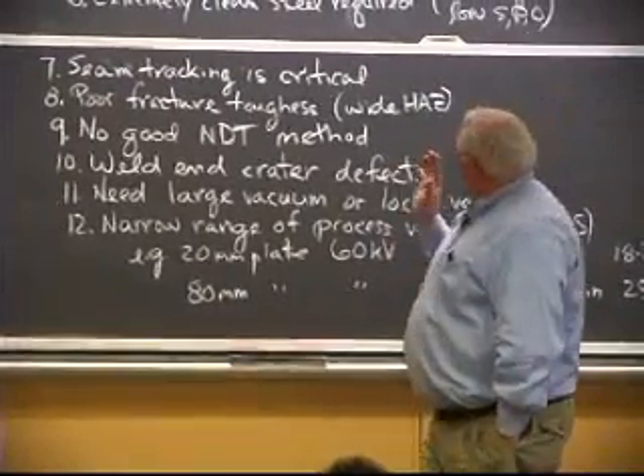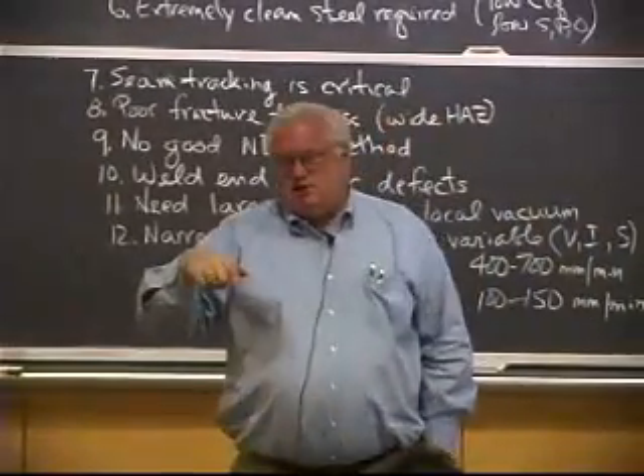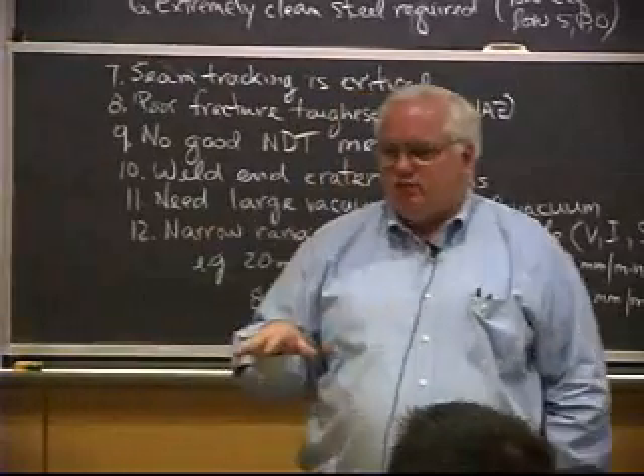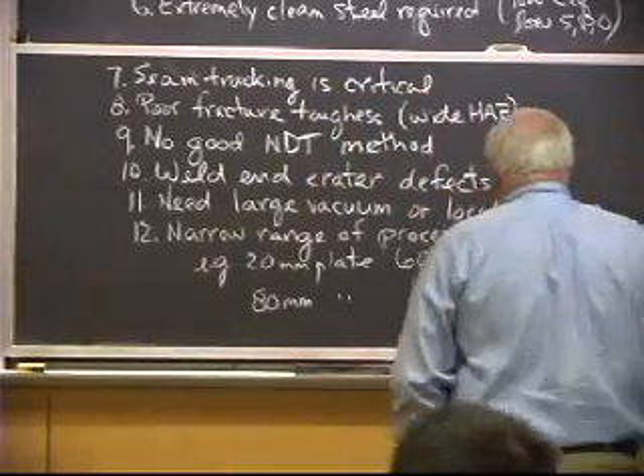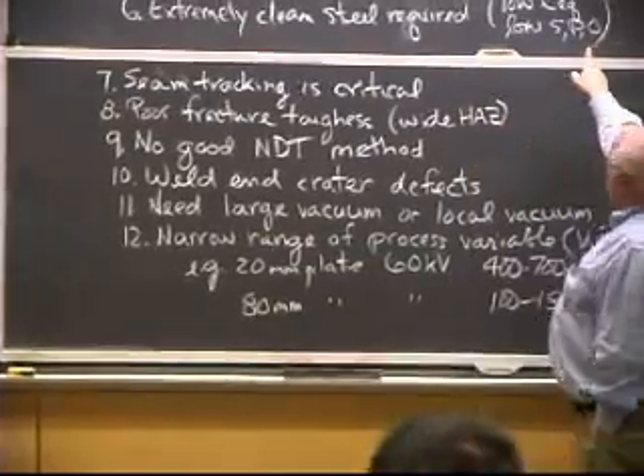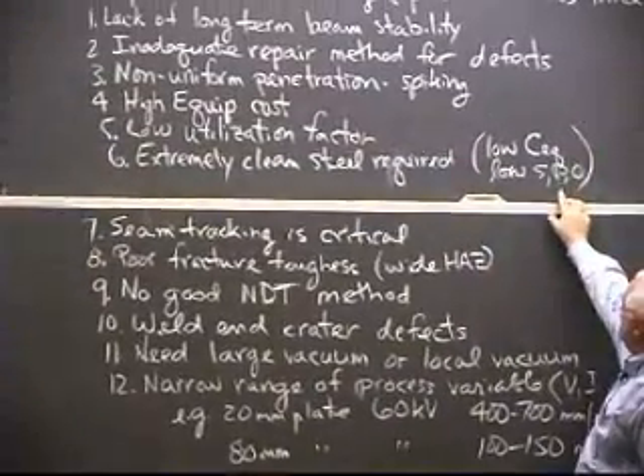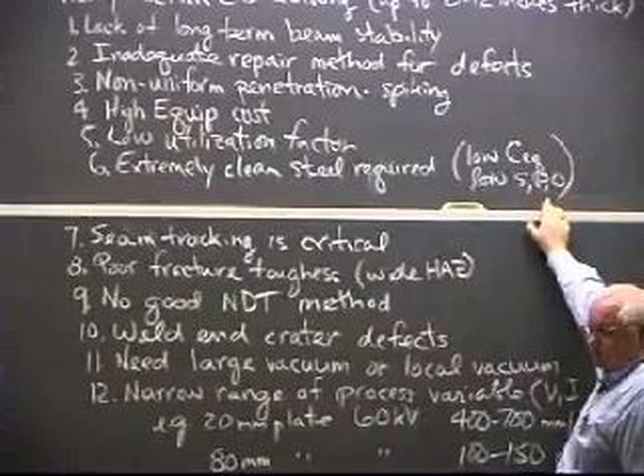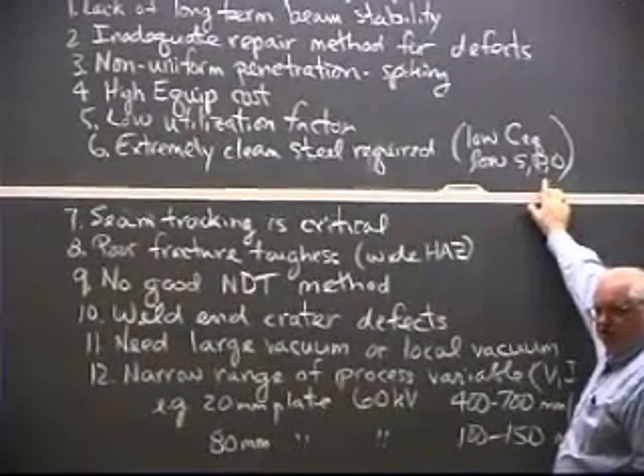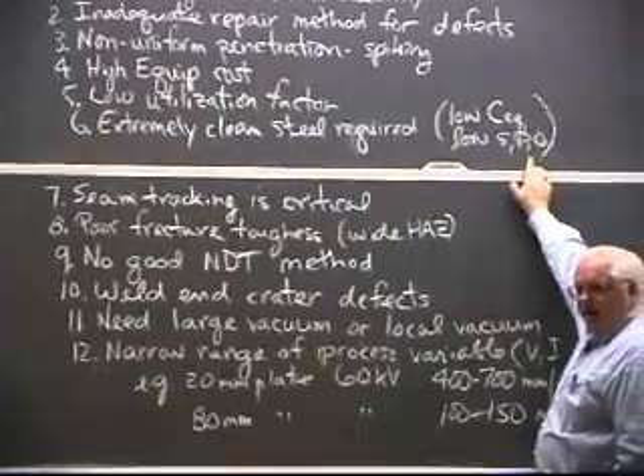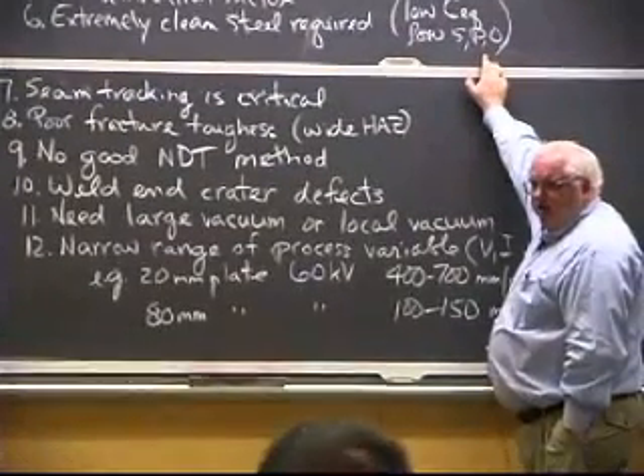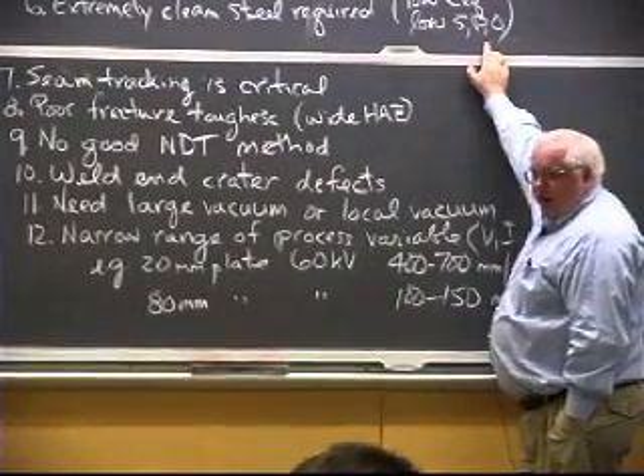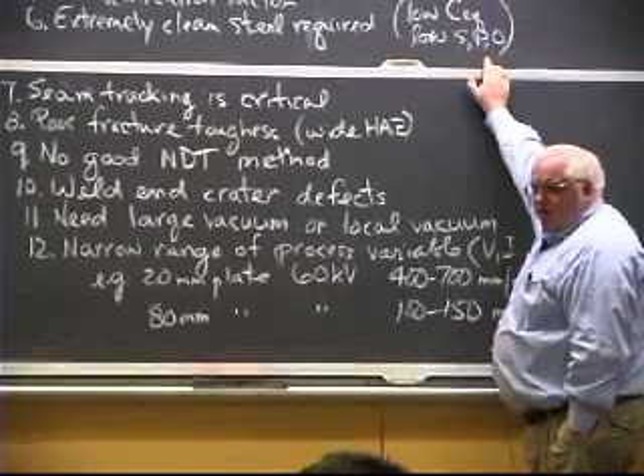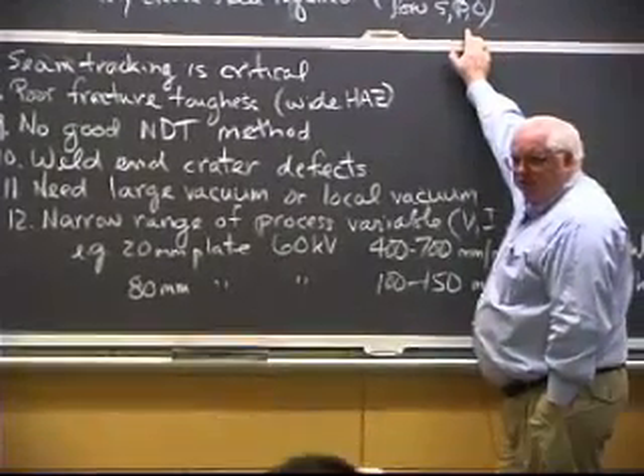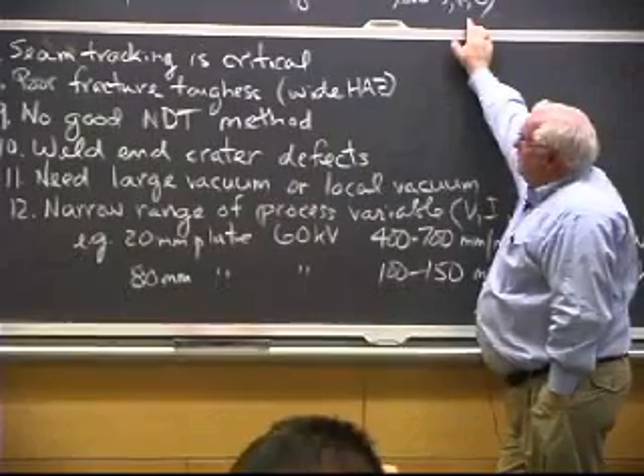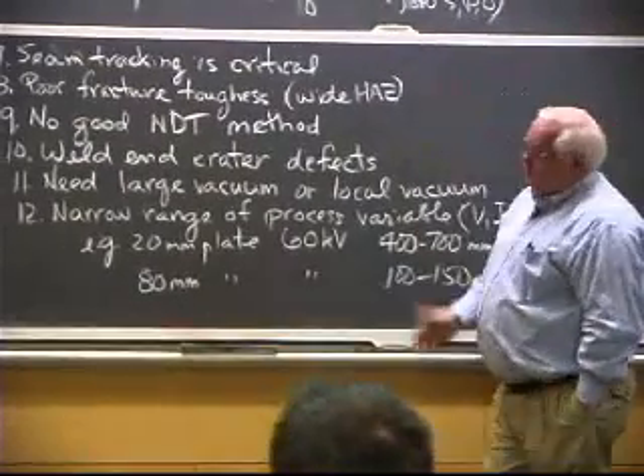They found that you needed extremely clean steel because you're superheating the steel to temperatures that it never saw in the steel making process. It turned out not only did you need a low carbon equivalent, which is a measure of your tendency to hydrogen cracking, but you needed extremely low sulfur, phosphorus, and oxygen, because at these higher temperatures you would start generating carbon monoxide gas and you get porosity. So unless you had very tightly controlled steel, which the Japanese were capable of making, it was not going to be a carbon steel vessel, it was going to be a very special steel vessel, and the costs were going to go up considerably when you're talking about something that's 8 inches thick and 30 feet in diameter.